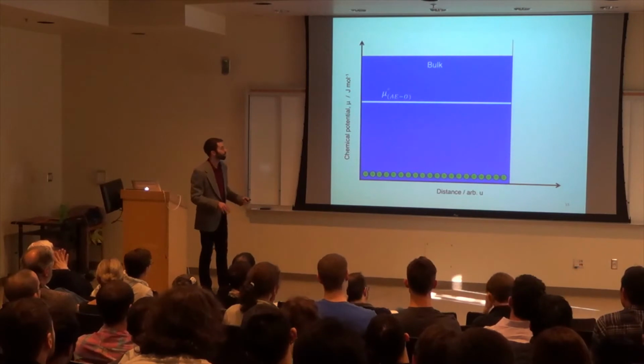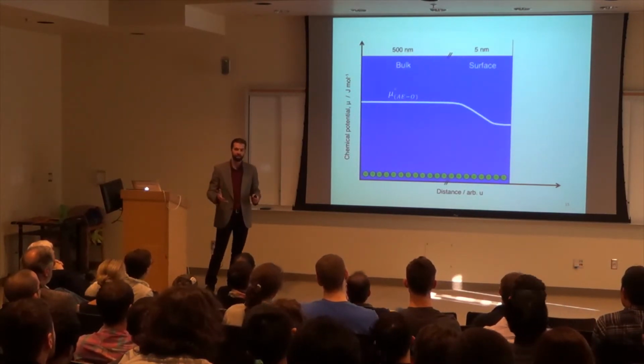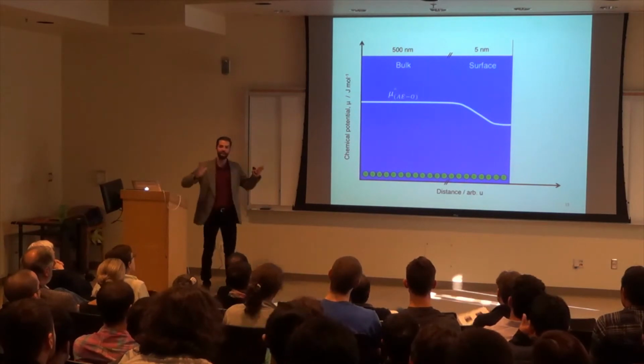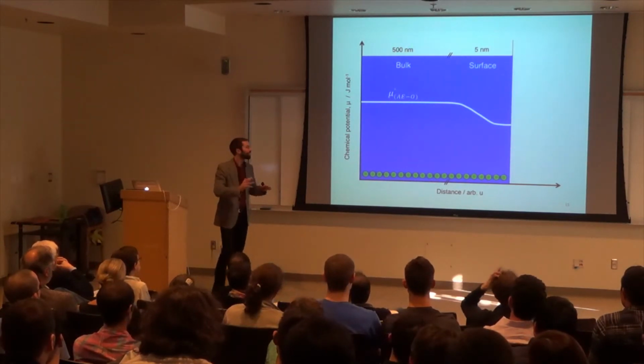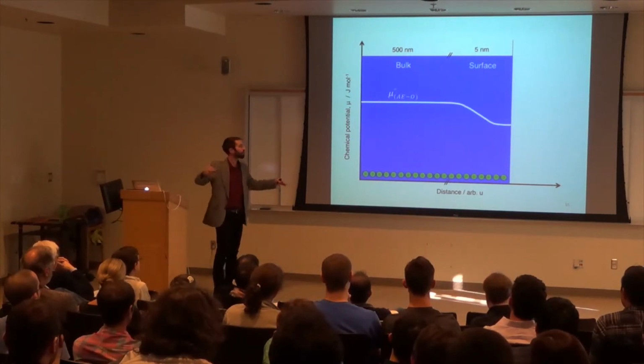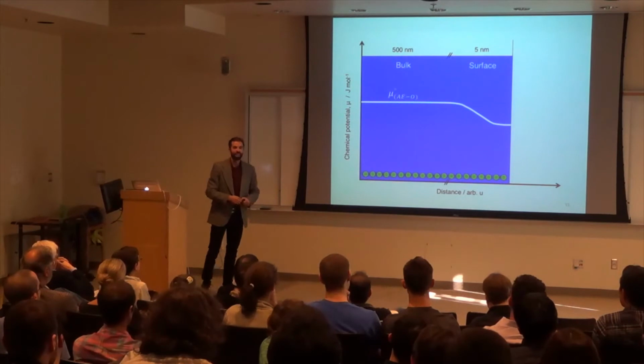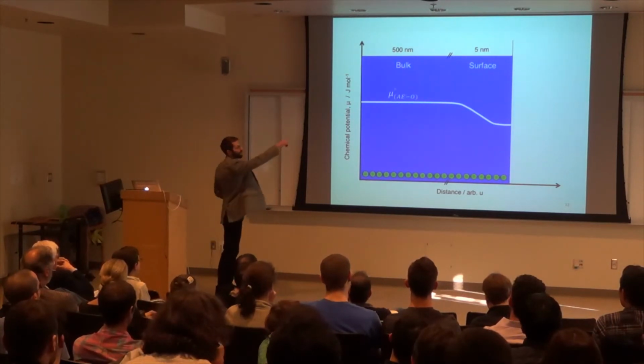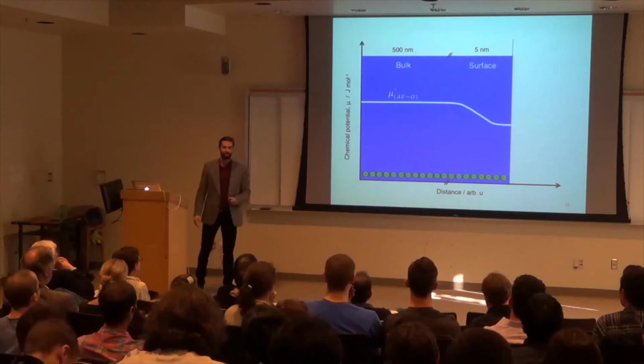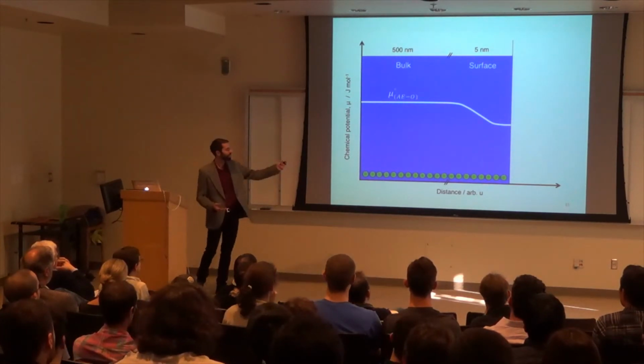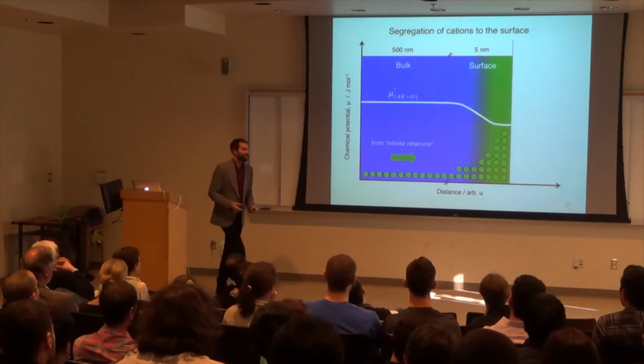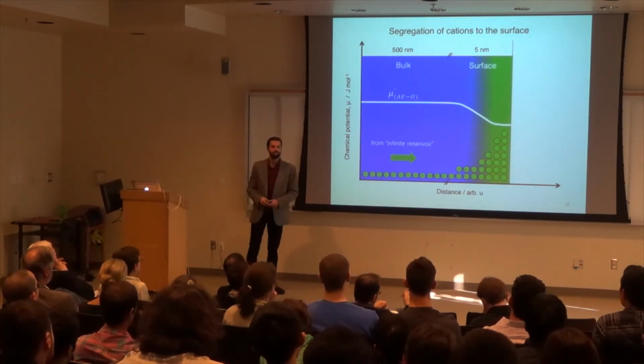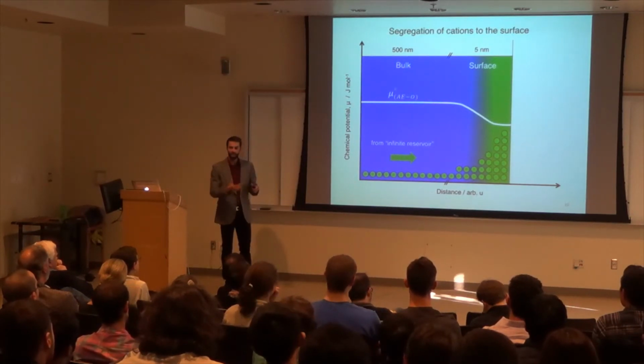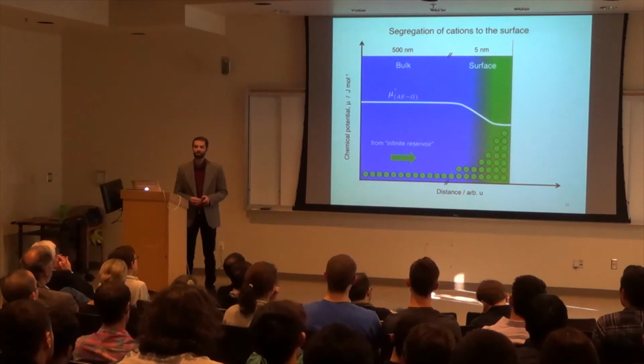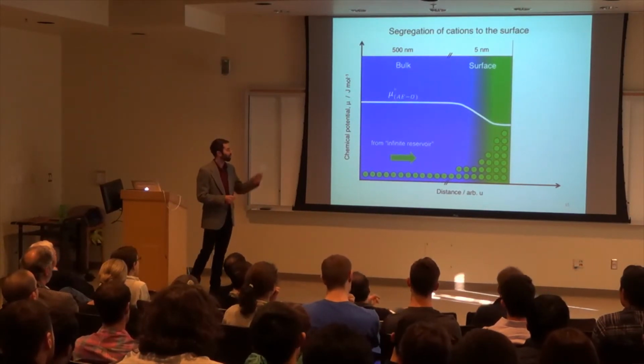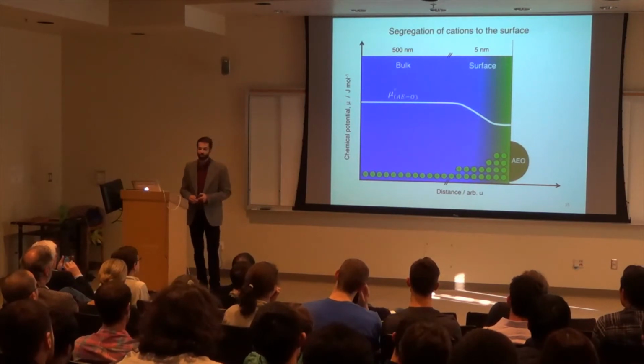Now as we move out to the surface, it is fundamentally different from the bulk, because it's essentially a two-dimensional defect where you don't have atoms crowding in and pushing everything together to hold it in place. And so the surface is a place where things can kind of expand out. And the chemical potential here essentially is a gradient to reflect that. This gradient down here means the driving force for things to drop down and become in a more favorable energy environment. So what we see, the distribution actually changes to something like this. The cations move from the bulk to this surface, essentially accumulating at the surface. And if they accumulate to a high enough limit, you reach a solubility limit where you can precipitate new phases.